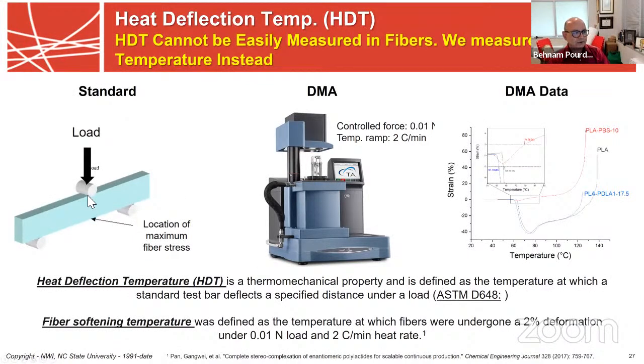We were interested in heat deflection temperature. You can, of course, measure it if you had a block of material using your classical 3-point bend test, but we're using a DMA. And actually, with the DMA, you can essentially see what really happens right about here. And so based on that, you can predict the heat deflection temperature of these materials.